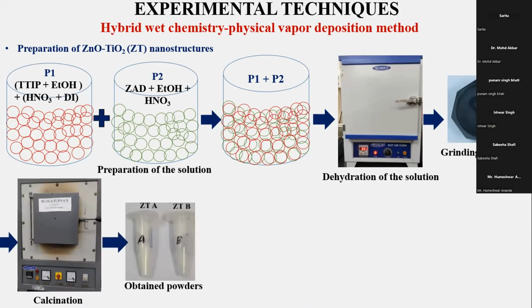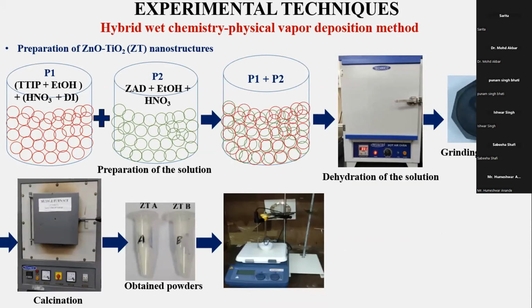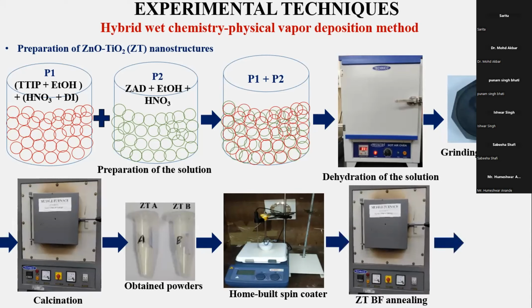you will get two particular powders under two particular conditions. And then we have developed a home-built spin coater method where we put some quartz and glass substrate on which we coat these particular powders we fabricated. And again, we do the calcination, and these are the particular films we developed on quartz substrate.